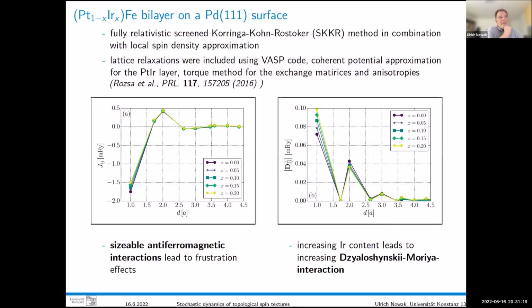So, for a specific material, we have now calculated all the interactions in the Hamiltonian. That is a lot of numbers that you have. It's not easy to get that from experimental facts or so. But you can do that with certain types of first principles calculation, for example with the SKKR method, fully relativistic, because you need the spin-orbit coupling. And that is work done by Levente Rózsa in the group of László Szunyogh, with whom we are collaborating.